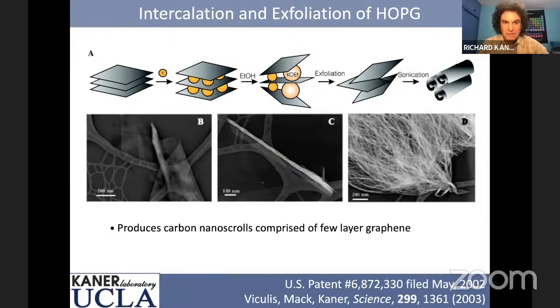When I told him I probably could make him a single layer of carbon, he asked me how that's possible. I said, well, it's been known for over 100 years that graphite is a layered compound and you can do intercalation chemistry. I just hit it with potassium: you can heat graphite with potassium at 200 degrees under inert atmosphere, and you'll make a first stage intercalation compound known as KC8, a bright gold compound. I said, I just take this material and exfoliate it. And he said, oh, that's a great idea, you've got to do that.